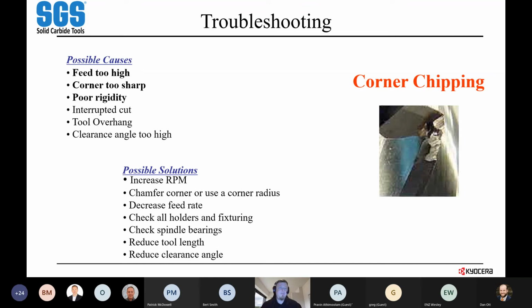Corner chipping. Traditionally, this is going to be an issue caused by too high a feed, the corner being too sharp, or just not having rigidity in your setup, whether it be on the part side or the tool side. Too much projection in the tool, too much tool sticking out. You can look at playing with your RPM, getting your chip load down a little bit. Also, if it's a roughing operation or a profiling operation, if you can get away with running a corner radius or a chamfer instead, then that's obviously going to add some extra protection to that corner, allow you to get through the cut, and then come back and finish it off with a square tool.